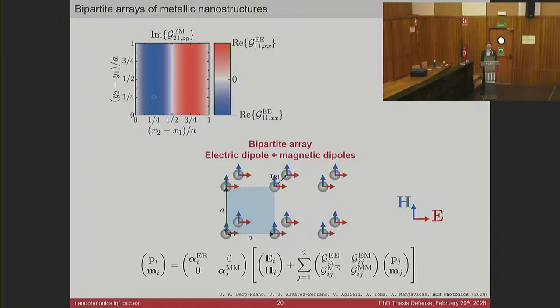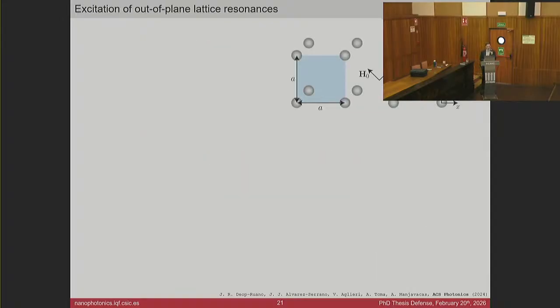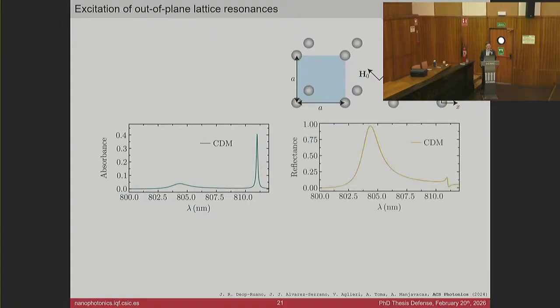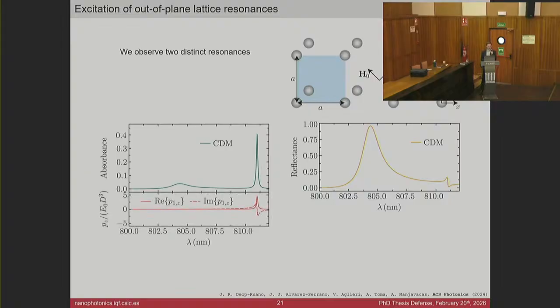The working principle is going to be the following. We are going to come with our electromagnetic field. We are going to excite in-plane magnetic dipoles, and thanks to this interaction, these magnetic dipoles will excite an out-of-plane dipole. Let's check if this works. I'm going to plot the optical response, the absorbance and the reflectance of our array. Now we have two distinct resonances, so to ascertain their nature, I'm going to plot the out-of-plane electric dipole. We observe that the out-of-plane electric dipole of both nanostructures attains large values in the exact region of this resonance that has a large absorbance, a small reflectance, and a narrower profile, the properties of an out-of-plane resonance.